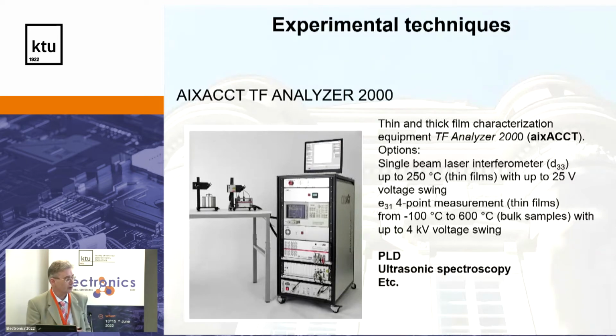And also in our lab, we have a pulsed laser deposition technique, where you can make thin films. So it's real nanotechnology, up to 20 nanometers or so. We have ultrasonic spectroscopy to measure ultrasonic properties, attenuation and velocity of the materials.